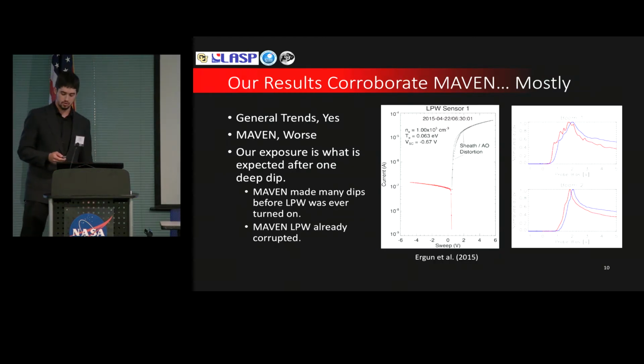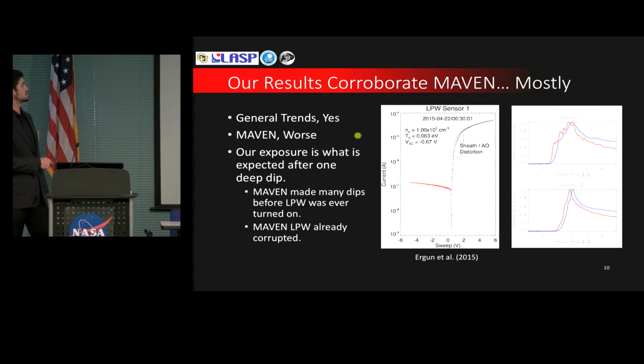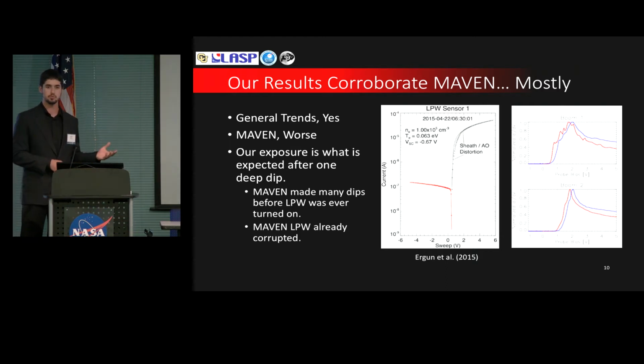Then comparing our results to MAVEN, they seem to corroborate almost everything except for the fact that MAVEN seems to be a whole lot worse. This is due to a couple of reasons. One, the Langmuir probes on MAVEN weren't turned on immediately. They went through several dips, over several months, I think, into the Martian atmosphere, testing other instruments before the Langmuir probes were ever turned on. So it's highly likely that any oxidation that would have happened had already happened.